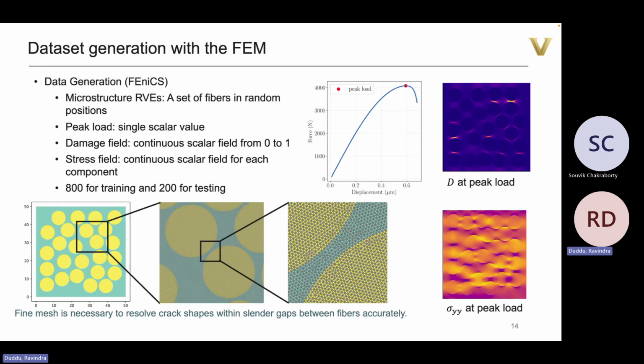And our hypothesis was that the damage or the stress field at the point where we have this peak load are somehow a good indicator of what that peak load has to be. Okay, so let me explain what that means in the next slide.